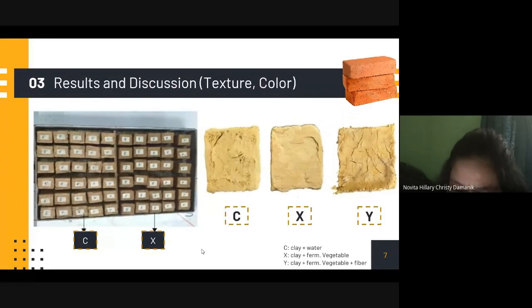Some other obstacles were on the Y samples. The potential for flimsy or fragile samples was greater than the samples without fiber, and it created small cavities. However, the positive was that the Y samples had a more stable shape compared to C and X. And then after days of curing, the samples were observed.